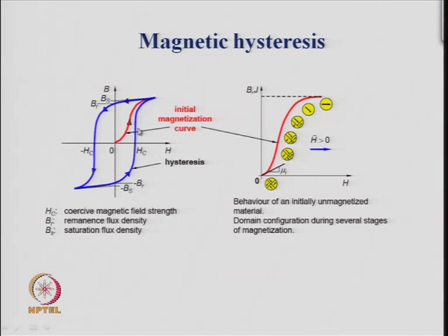And if you look at this plot, what is the type of magnetic dipoles that you have, what is the orientation of the dipoles at different stages of this plot can be seen here, especially the red plot, the initial magnetization when you started from 0 magnetization, the material was not magnetized earlier. So, first time when you magnetically pull the material, you apply a magnetic field, you go through these steps. So, you see initially at 0 field, there is 0 magnetization because all these vectors are in different orientations. Now, when you increase the magnetic field, then some of these dipoles gain in strength. You see this region is becoming larger.